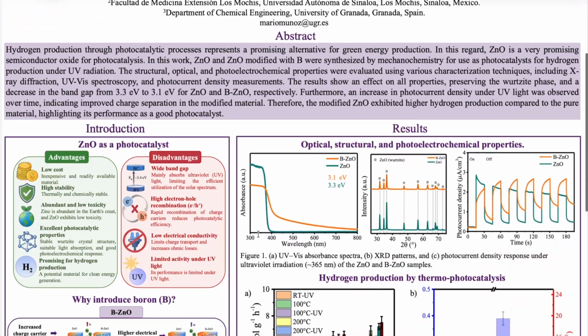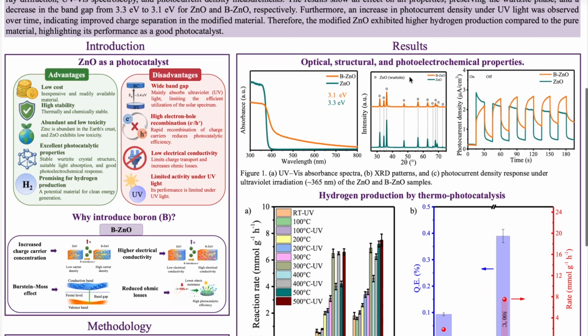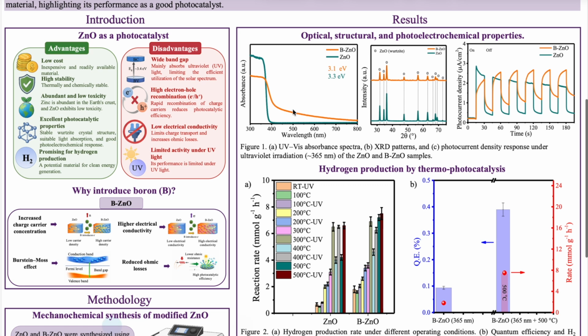Results. Now I would like to present the main results of this work. Figure 1a shows the UV visible absorption spectra. The boron-modified material exhibits a slight reduction in the band gap, decreasing from approximately 3.3 electron volts for pure ZnO to 3.1 electron volts for boron-modified ZnO, which favors light absorption. Figure 1b presents the X-ray diffraction patterns. Both materials preserve the characteristic Wurtzite crystal structure, indicating that boron incorporation does not alter the crystalline phase of ZnO.